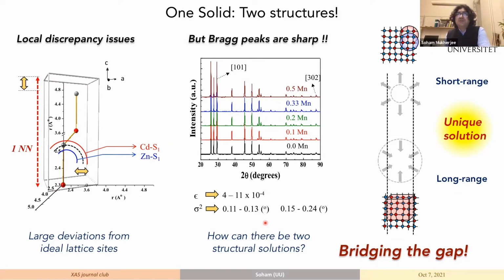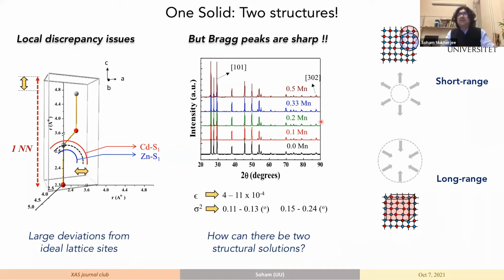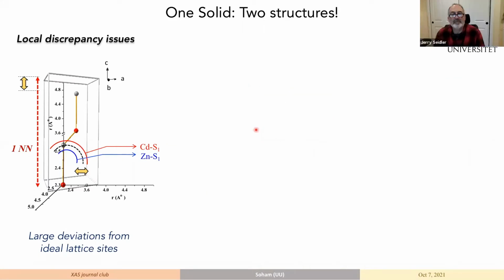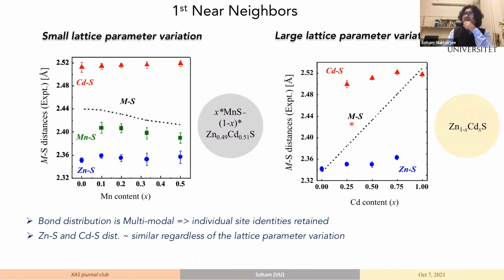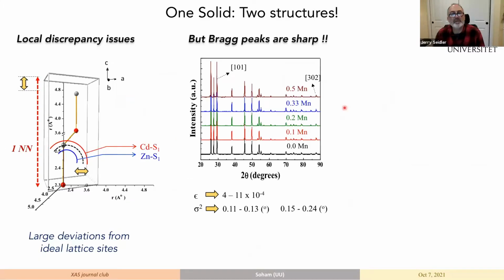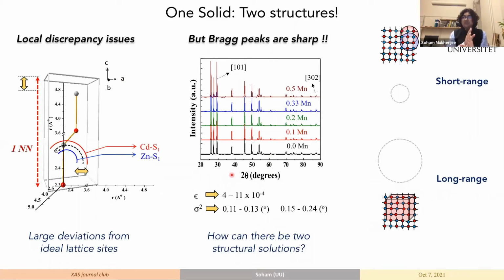But what I'm trying to say here is that when we have two different distances, when we're looking at the local bonds, there's nothing fancy going on as far as the periodicity is concerned. Because when you see the difference between the two bond lengths from zinc sulfide and cadmium sulfide, you can see the difference between the two bond distances is roughly around 0.2 angstroms, right? And that is an enormous amount of change for a unit cell. At that kind of distance, you would expect the unit cell to collapse when the two atoms are coexisting in the same unit cell. So the motivation for this particular slide was to show that the diffraction peaks are still quite sharp, and the sample is perfectly crystalline.